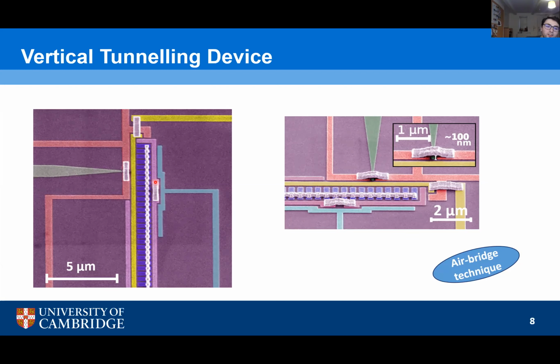So essentially, the first stage is pretty straightforward, mesa ohmics, and we have a first E-beam stage to fabricate all these gates. We've had trouble with this mid gate here that kept breaking. You need to make sure that it goes into the split gate, so the mid gate here in green, split gate in red, and the barrier gate in purple. You need this in order to ensure that you have tunneling. Otherwise, you can't have independent ohmic contacts.